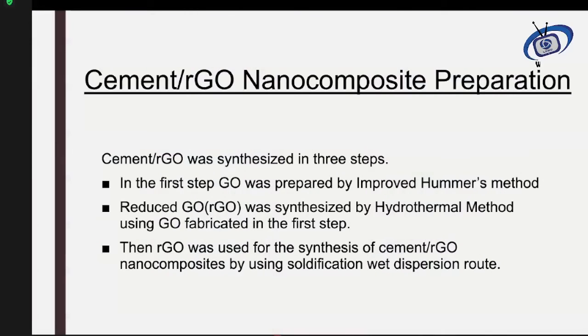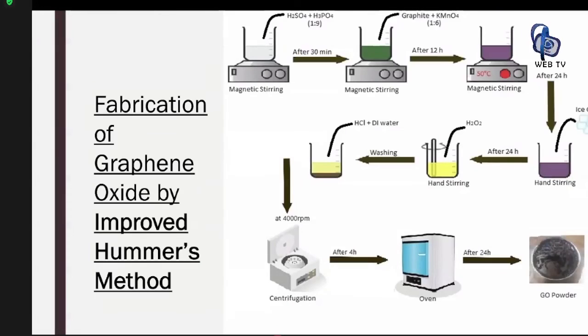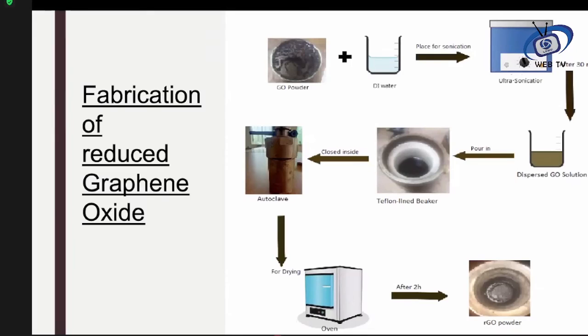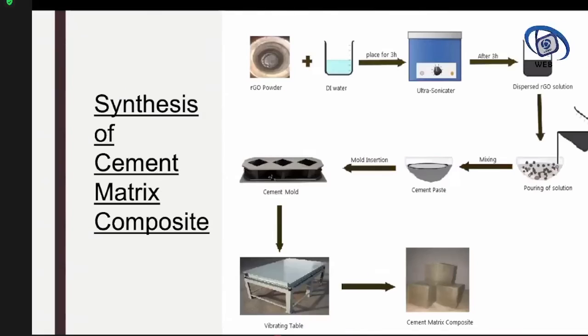This is a schematic diagram with the help of which the improved Hummers method was used to produce the graphene oxide, and then that graphene oxide was reduced by using the autoclave, and then it was mixed into the cement to produce these cubical cement blocks.